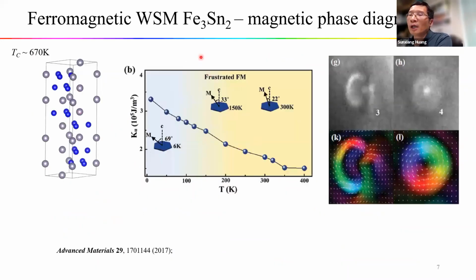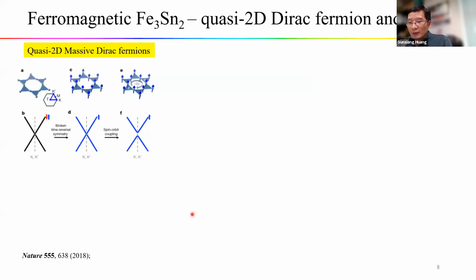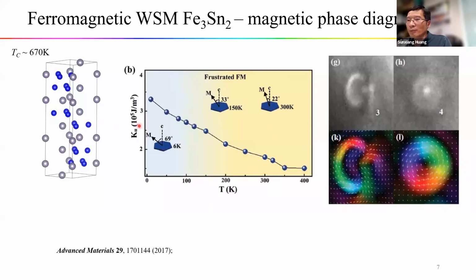Now let's move on to the next material, the magnetic Weyl metal Iron-tin. It is a magnetic material with a Curie temperature of about 670 K. It's really high, so that's good for application. For the bulk single crystals, the magnetic axis rotates from the c-axis at low temperature towards the in-plane at high temperature. Interestingly, if we apply the magnetic field along the c-axis, we can observe rich spin textures, such as the magnetic skyrmions observed by Lorentz TEM measurement. This is the real space spin texture in this compound.